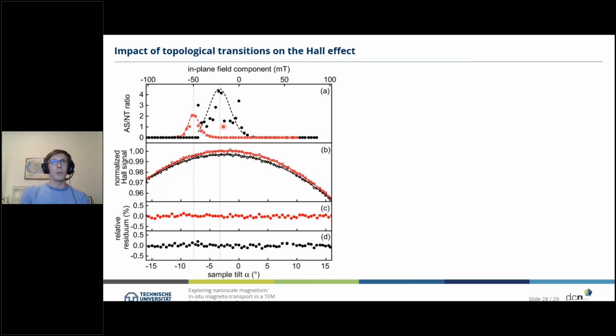And at the same time now we measured the anomalous Hall effect, which is shown here in the central panel, which of course follows the cosine behavior, since we tilt a ferromagnetic sample and therefore get different out-of-plane components.